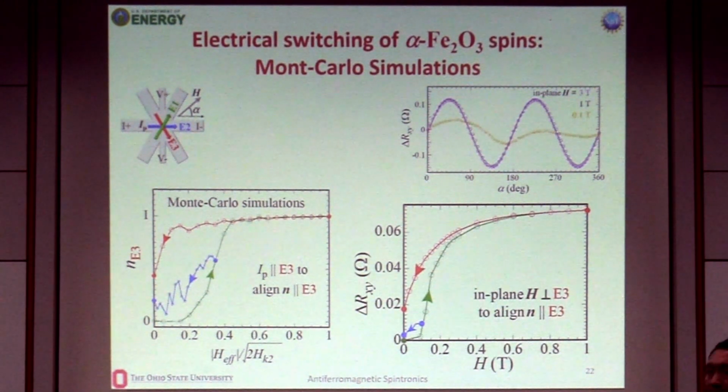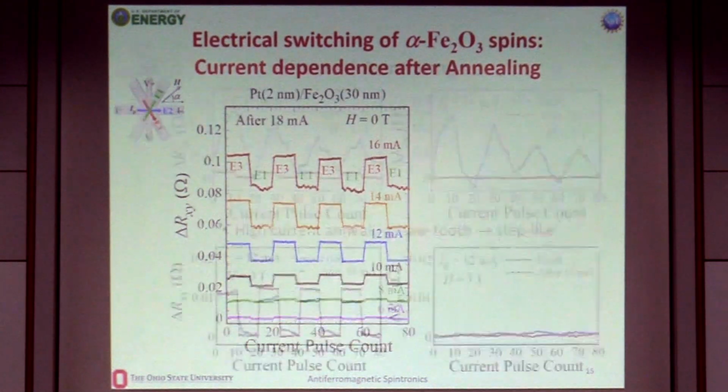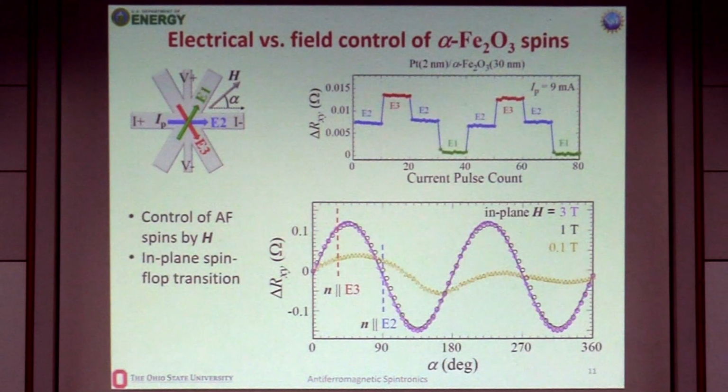Last question. Did you look at relaxation of the electrically switched domains? Relaxation meaning just waiting, without pulsing. We have done, I think my students have done, like 500 pulses, and they stay basically the same. Not perfectly the same, but they stay in a plateau, like the first one we showed, something like this. It stays like a plateau for 500 pulses. So you just measure... Yeah, we pulse a number of times, like 1 or 10, and then keep measuring every 30 seconds. It's going to stay. Yeah, that's stable.